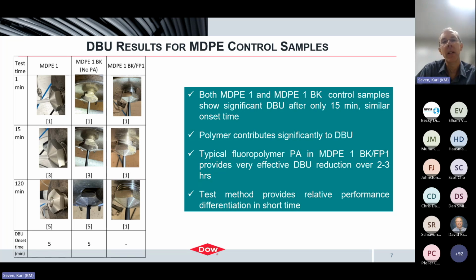The last series of pictures is basically a comparative sample. That's the fully formulated jacketing compound with the typical fluoropolymer-based processing aid. And so, as expected, this shows virtually no buildup over the entire test period. And so this is kind of just showing that this test method can provide relative performance differentiation between samples within a relatively short amount of time.